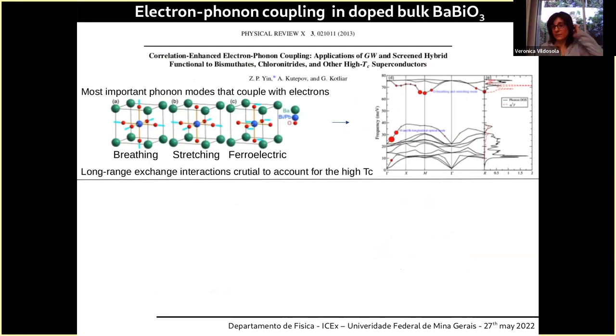So we started to calculate the electron-phonon coupling of this material. The electron-phonon coupling of this material already in bulk was studied before. Here is Gabi Kotliar, that Walter knows very well. They studied it because up to this year, GGA calculations were not able to describe properly the electron-phonon coupling of BBO.